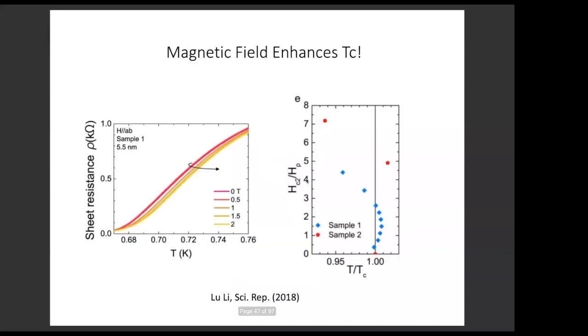But it's interesting that the same year, there's another experiment from the Michigan group on epitaxially grown thin films of tungsten ditelluride, about 5 nanometers thick. And these authors actually realized that there's a magnetic field enhancement of TC, and that was the focus of their work. And they met tremendous trouble with referees. This is my understanding from talking to Lu.